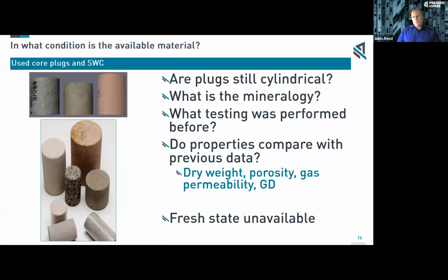And so what we will do is do a pre-study to look at that. Then consider those properties again. So measure the properties, look at things like the dry weight. Is the dry weight the same, or the grain density equivalent to the previous data? The porosity and the gas permeability. Now, these are being performed on samples where these measurements have been performed before. And so we should have a direct comparison, and they should be equal within standard measurement error.